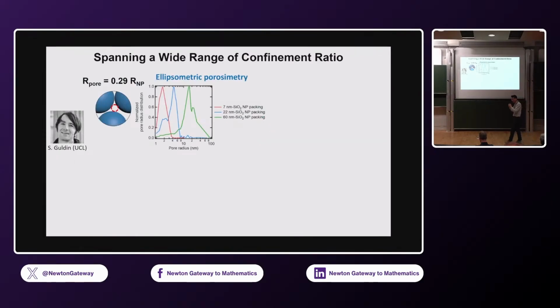What's really interesting about this nanoparticle packing is it's porous. The characteristic pores of random close-packed spheres is known to be approximately 30% of the size of the particles. So if your particle size is 10 nanometers, you have on the order of 3 nanometer pores. And we've actually experimentally confirmed this in collaboration with Stefan Guldin, who was at UCL at the time, using ellipsometric porosimetry. Okay? So you can see that as we change the size of nanoparticles that we are using, the size of the pore changes systematically.